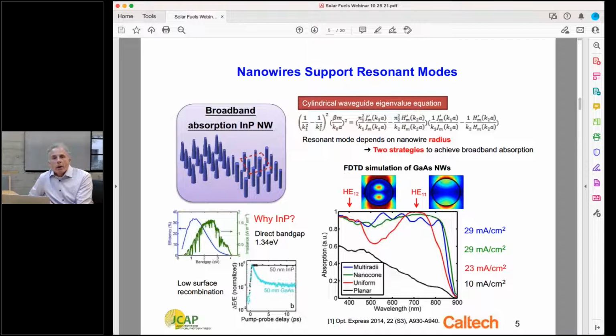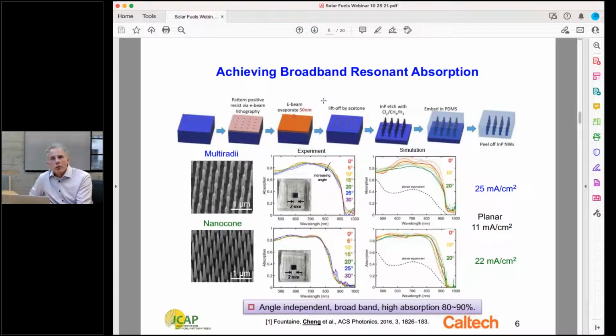And if we add up organ pipes that are at different tones, we can generate optical absorption where there are individual resonances denoted by these peaks here, such that a multi-resonant array can span the entire solar spectrum up to the band edge of the absorption of the semiconductor, in this case indium phosphide. And this just shows some experimental results for a patterned indium phosphide array where we're able to essentially get near the limiting photocurrent in a nanowire array, whereas the planar equivalent thickness material of indium phosphide has about half the photocurrent.